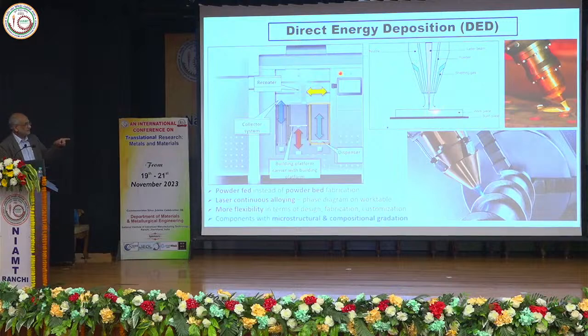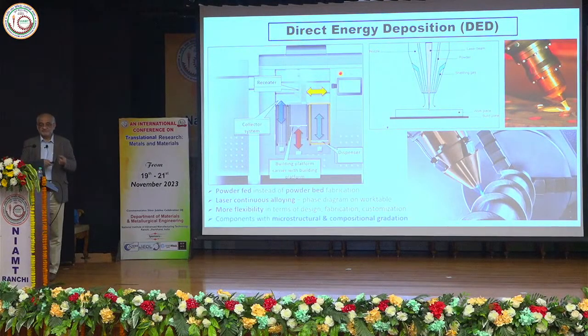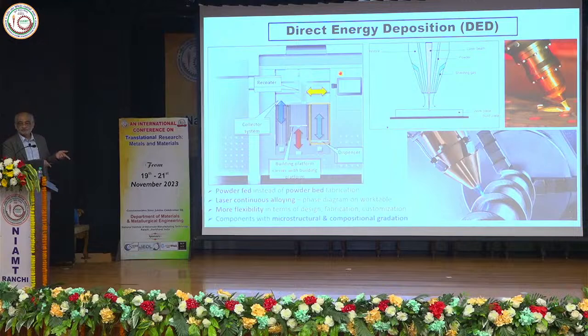So this is where the trick lies: I can have multiple feeder nozzles, feeding not necessarily the same powder, different powders. Even during feeding, I can keep changing the proportion of A, B, C, so I can vary the composition. Even in the simplest case, when I'm feeding the same stainless steel from 4 different nozzles, I have to make sure that the point where the powders are converging, the laser spot should also coincide exactly at that. So there should be a total coincidence or convergence of the laser beam and the powder feeding point.